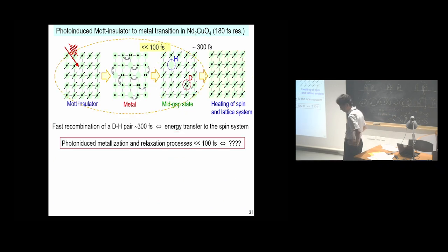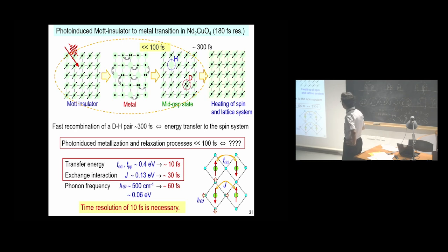Next important issue is to clarify the photoinduced metallization and relaxation processes in this initial time region. In this compound, the time scale of the transfer energy is about 10 femtoseconds, and that of J is about 30 femtoseconds. So, in this process, the charge spin coupling would be also important. So, it is important to detect the charge and spin dynamics.